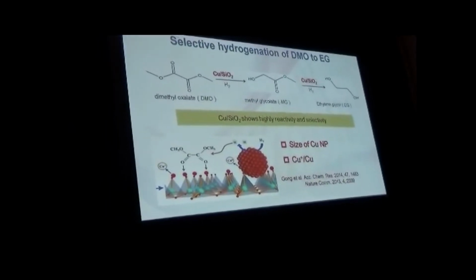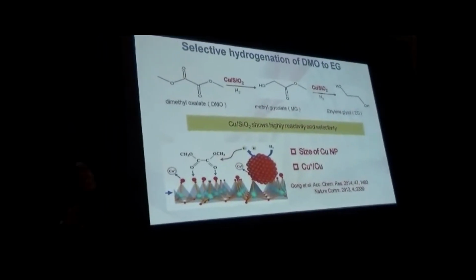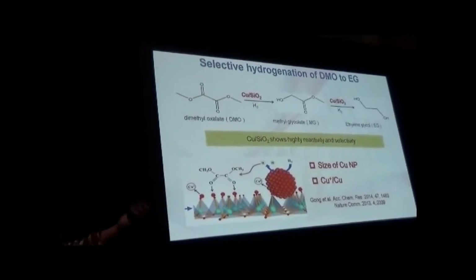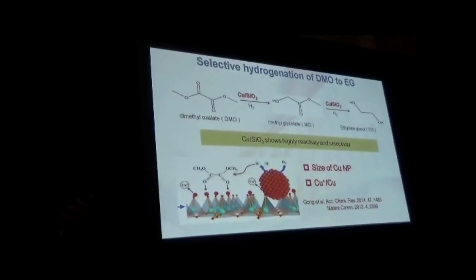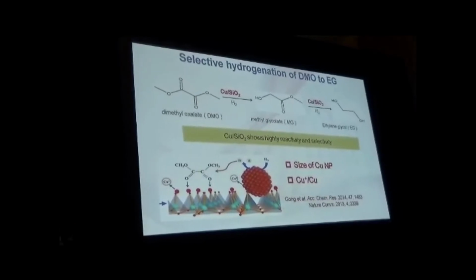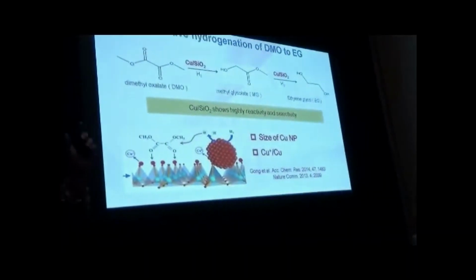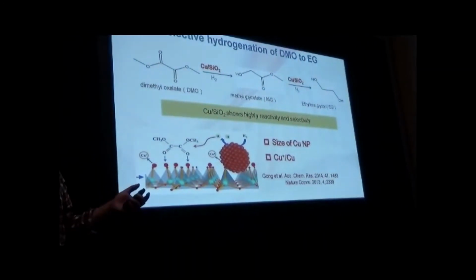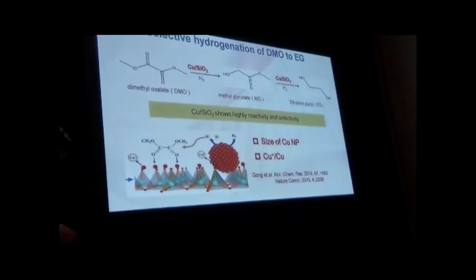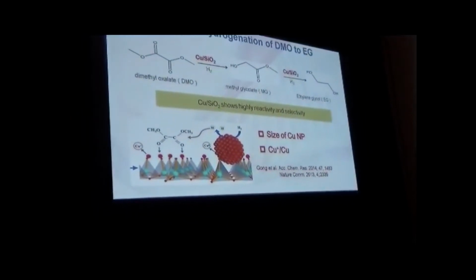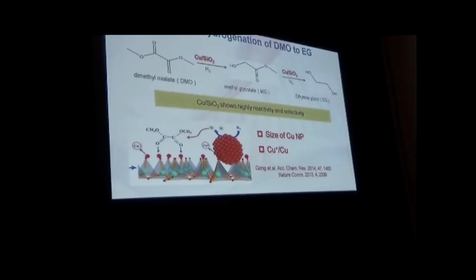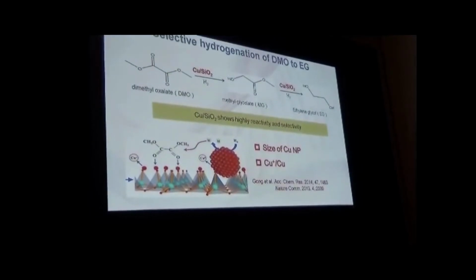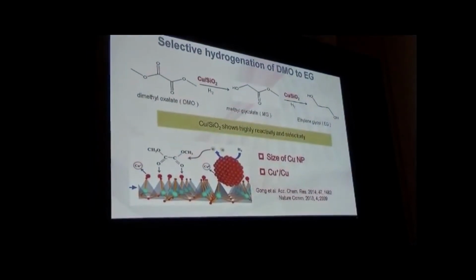Yeah, we can find that we can replace the silica with other oxides, but the performance is not so good. Copper/silica is one of the best catalysts for this reaction. Why? Because in previous work, people claimed that silica will help the copper disperse into nanometer size. So it's the nano effect, because the size of the copper nanoparticle is very important.